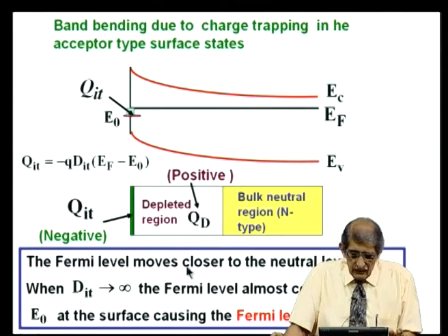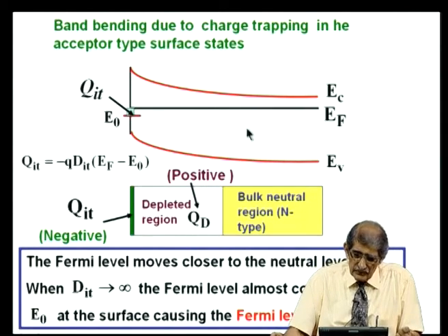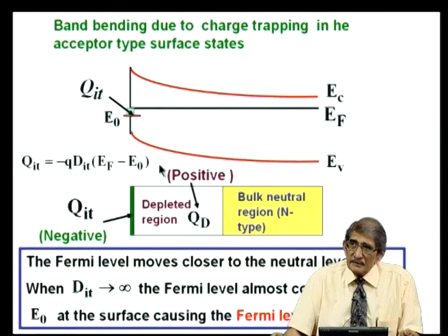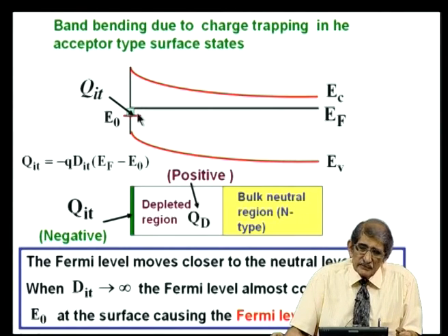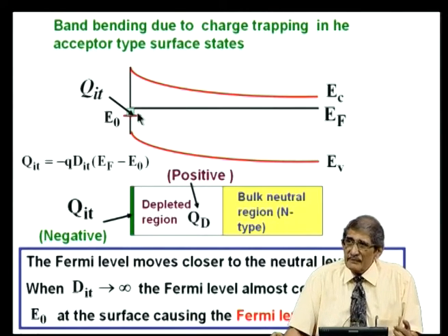So, you can see that the Fermi level moves closer to the neutral level E naught. Supposing dIt is tending to infinity, with a very small gap between E f and E naught, you will get the required charges for the depletion layer. It can never coincide with E naught, but it will get closer and closer. If dIt tends to a very large value, E f minus E naught tends to 0. In the sense, the Fermi level moves closer and closer to this E naught. So, you say if dIt is very, very large, the Fermi level gets pinned to the E naught level. That is called Fermi level pinning.